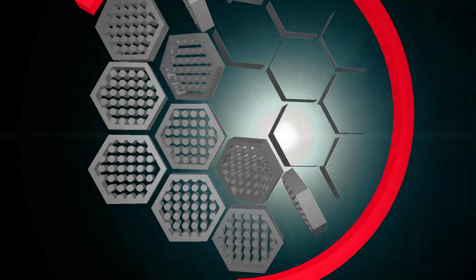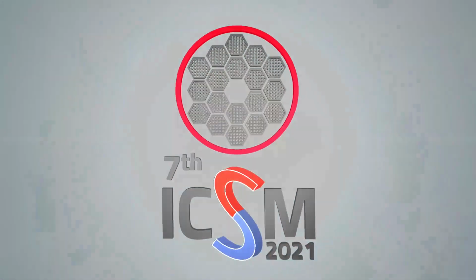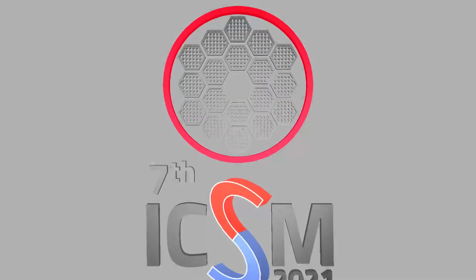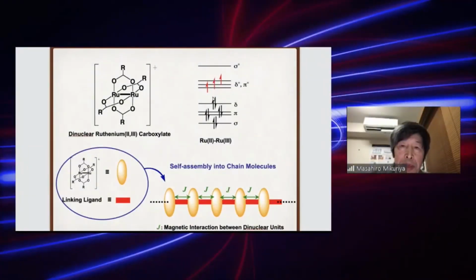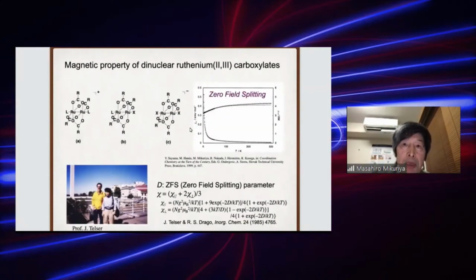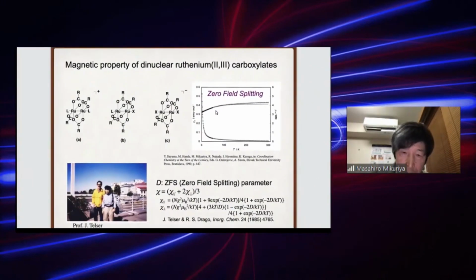Dinuclear compound. In case of ruthenium, this dinuclear unit has three unpaired electrons between ruthenium bonding, and we can use this unit to make some magnetic compound. So this unit has zero-field splitting, so magnetic behavior like this, and this was analyzed by Professor Telser for the first time.